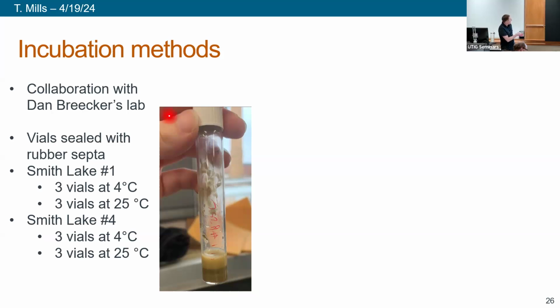And then we've taken 2 samples, one from each site, to incubate. For those incubations, we took from Smith Lake 1, from one stratigraphic horizon, and we are incubating those at 4 degrees C, so refrigerated, and at 25 degrees C. And then we did both of those in triplicate, so we can average the values together. And then we did the same thing at Smith Lake 4.